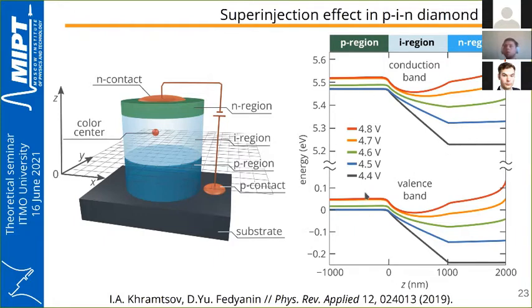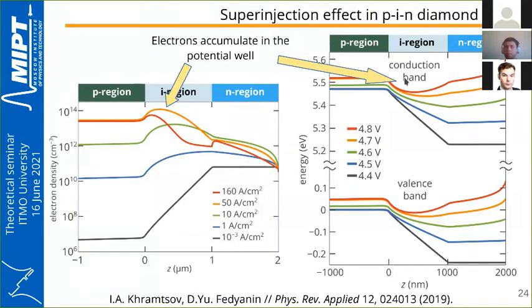At low bias voltage of 4.4 volts, this is just a typical band diagram with the conduction band edge and valence band edge. But when we apply higher bias voltages, a potential well for electrons appears in the I region, where electrons tend to accumulate, as shown by the electron distribution at different currents. The electron density can reach 10^14, which is 3-4 orders of magnitude higher than can be obtained in the N-type region during doping.